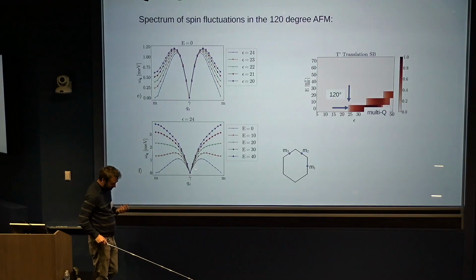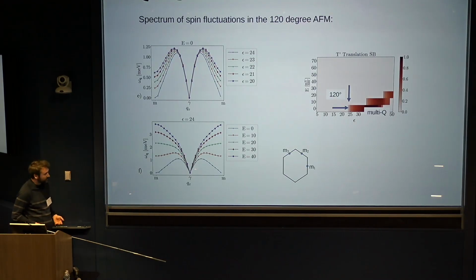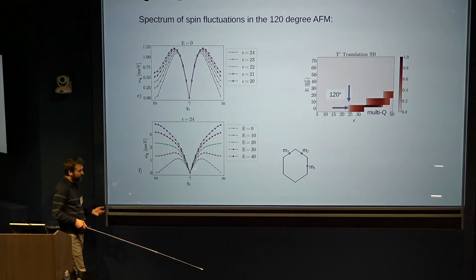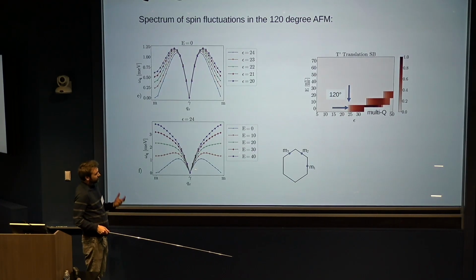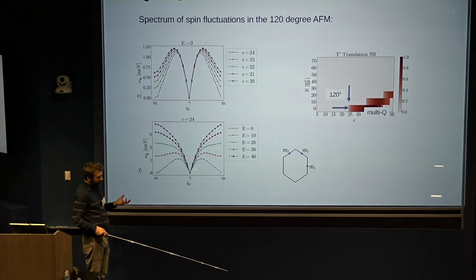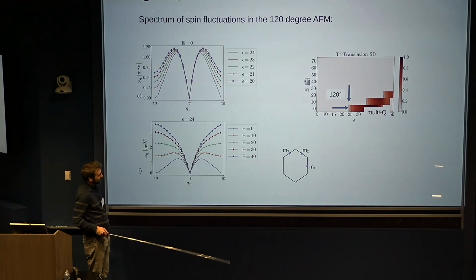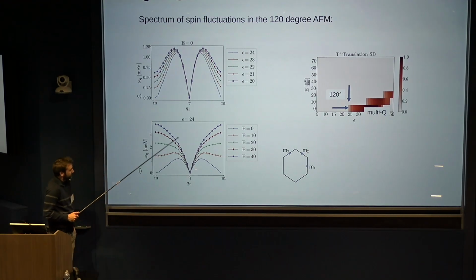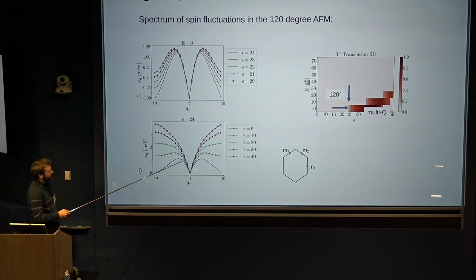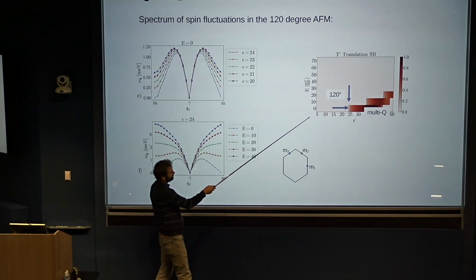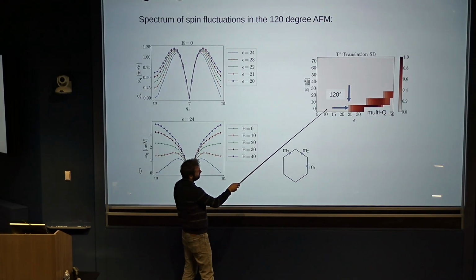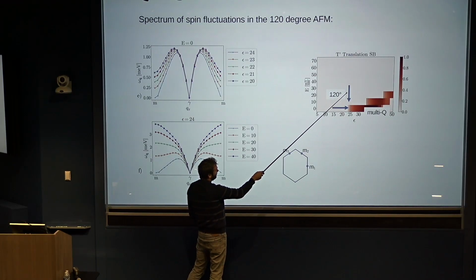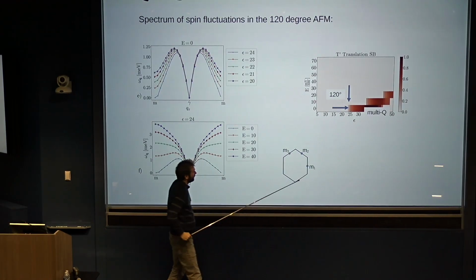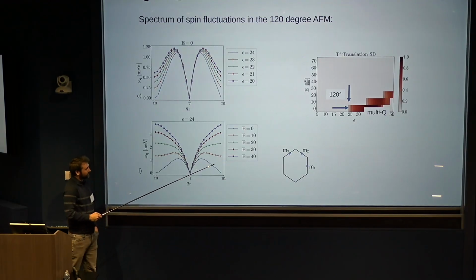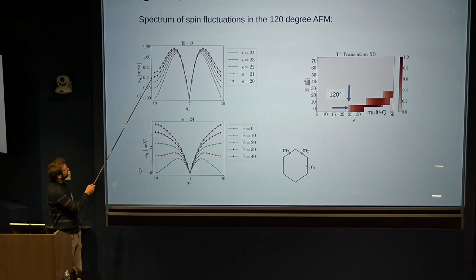The reason I'm talking about magnetism at basically a collaboration about superconductivity is that I believe there's a very strong connection between this magnetism, or the magnetic fluctuations, and the superconductivity. And the reason that I believe there's such a connection is that if we start in this 120-degree AFM, and as we approach this multi-Q state, this multi-Q magnetism, we see that it's accompanied by continuous softening of the spin fluctuations at the endpoints.